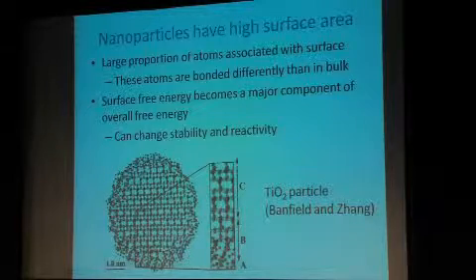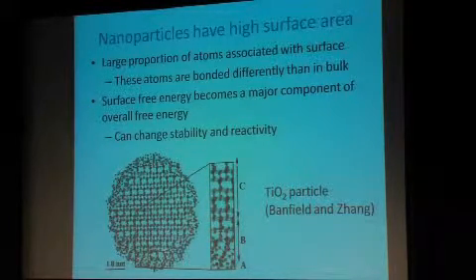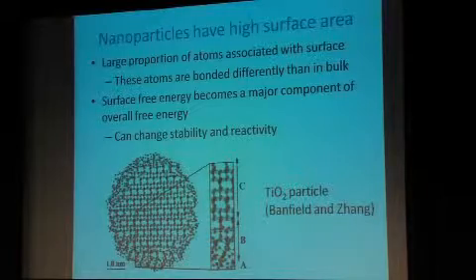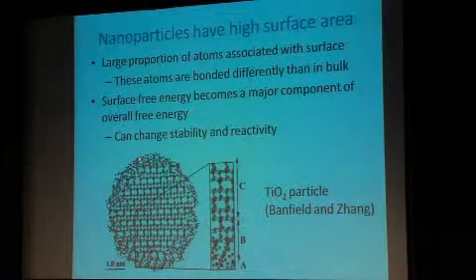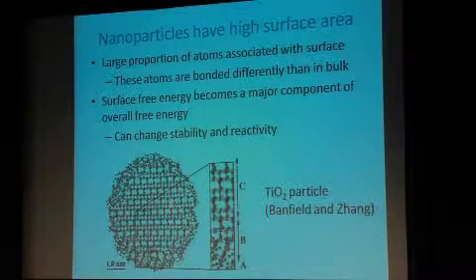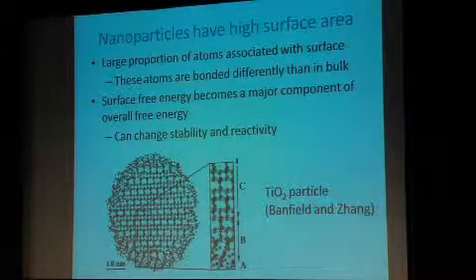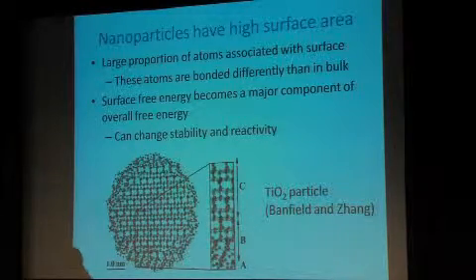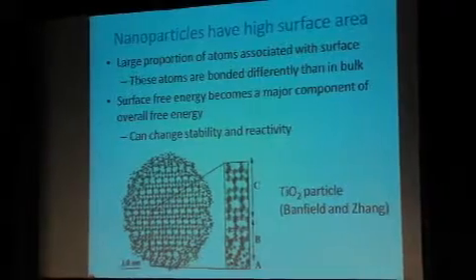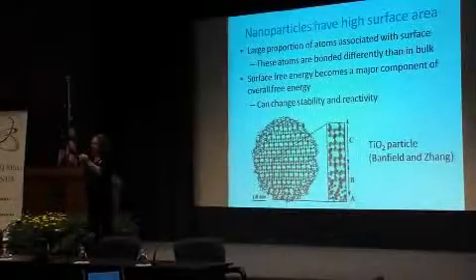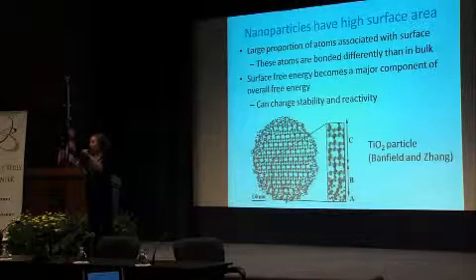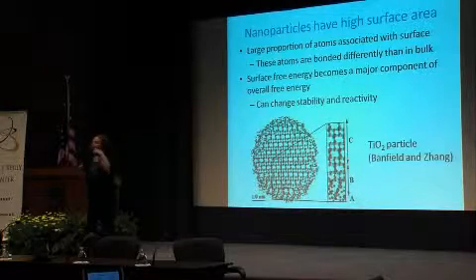When you get to small titanium oxide particles or any mineral particle, you get a larger proportion of atoms associated with the surface. The atoms that are associated with the surface are actually bonded differently from how they are in the bulk. So when you have a large particle, you've got this surface that's bonded differently from the bulk, and it's going to change its properties, its reactivity. But when you have a small particle, a very high percentage of the total particle is surface, you've got a lot of different bonding than in the bulk. And that's why surface area matters more than just surface area alone.